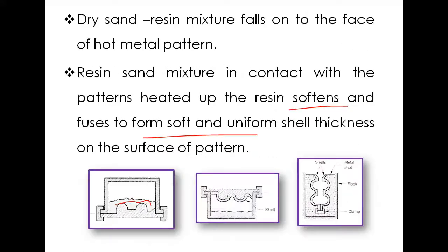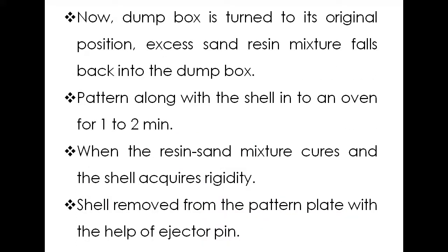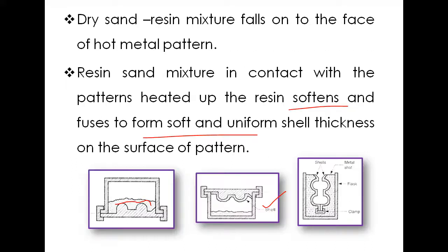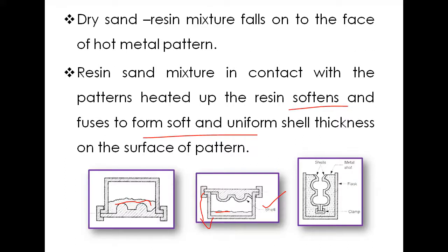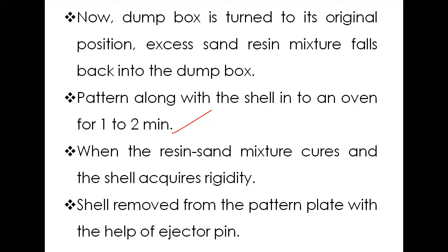Now the dump box is turned back to its original position. The excess sand resin mixture falls back into the dump box. Next, the pattern along with the shell is taken from the dump box and kept in an oven for 1 to 2 minutes, because the resin sand mixture cures and hardens. When the resin sand mixture cures, the shell acquires rigidity.